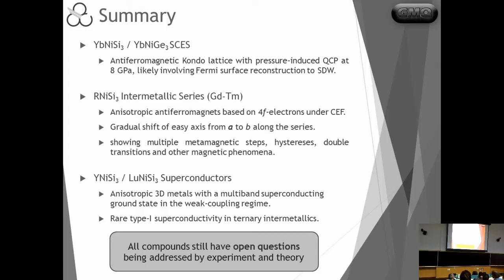For the superconductors, as I said, these are anisotropic 3D metals with a multiband superconducting ground state in the weak coupling regime, and rare cases of type 1 superconductivity in ternary intermetallics. And all of these compounds, literally all of them, still have a lot of open questions that we are addressing both experimentally and theoretically.